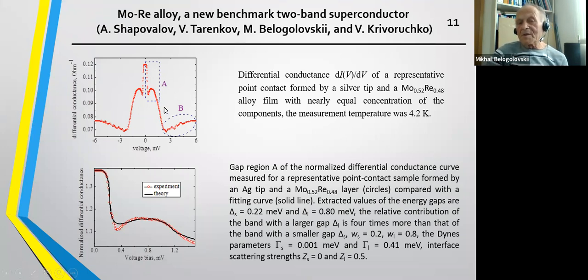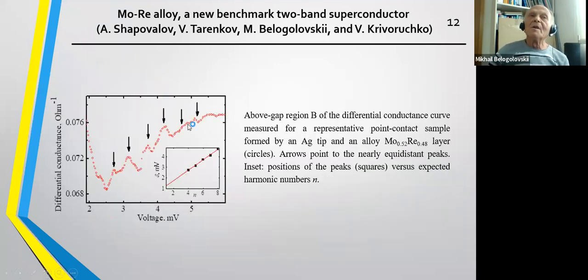This part reveals, in our opinion, two gaps at a sufficiently great distance. And here a periodic structure was observed, and this periodic structure was assigned to the so-called Leggett mode. The Leggett mode was proposed in the 60s by Leggett, and the idea is that if you have interaction between two bands in a superconductor, between two gaps, there will be some oscillation relative to the difference in phases of the two groups of superconducting condensate.